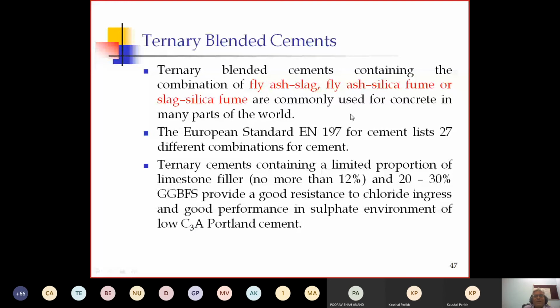Combinations of cement with fly ash and slag, or fly ash and silica fume, or slag and silica fume are commonly used for concrete in many parts of the world. The European standards, of course, our standards are not available, but European standards are used for getting mix proportions and other related criteria. For cement, they list 27 different combinations, and ternary cement containing a limited proportion of limestone filler and 20 to 30% GGBFS provides good resistance to chloride ingress and good performance in the sulfate environment of low C3A Portland cement.